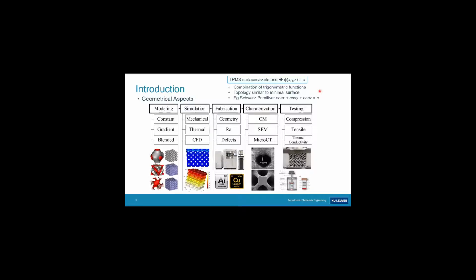And one kind of lattice structure you could use for that, because it aims at optimizing the surface area per unit of volume, is the so-called triply periodic minimum surface functions, which are basically a combination of trigonometric functions in 3D. The simplest one is the primitive Schwarz surface, which is just a combination of 3 cosine functions in 3 directions, equaling a certain constant, and as you modify the constant, you actually change the fraction of the 2 composing volume units.